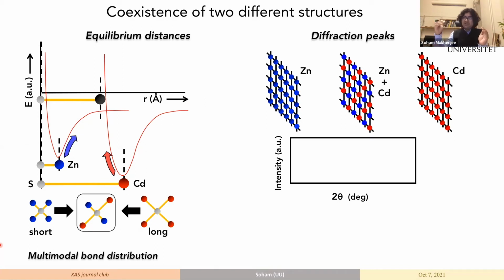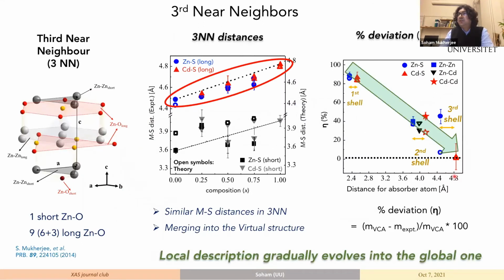So the approximations that we developed based on that, which are the virtual crystal approximation and the coherent potential approximation, these models took that description and boiled it down to individual bond distances. And that is where it essentially breaks down. Now, this doesn't mean that the periodic definition is wrong. It's absolutely correct, because when you are doing diffraction, what these models are predicting is a volume averaging technique at the length scale of 50, 60 angstroms, but we are operating, if I show you the length scales, at around 5 angstrom length scales, right?